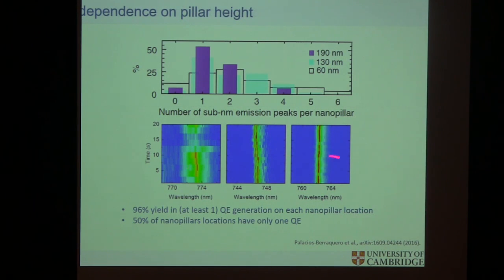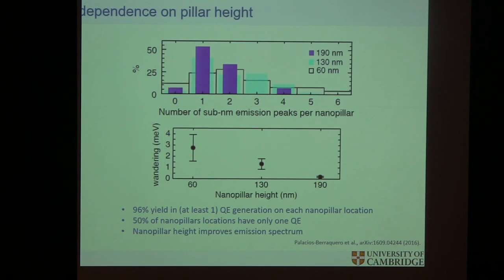The second thing, more unexpected one, is the quality of the light that comes up. Higher the pillar, cleaner the spectrum. The spectral diffusion is suppressed. This is the same scale, essentially, almost. Yeah, it should be the same scale, that's right. This is for 60 nanometer pillar, 130 and then 190 nanometer pillar, really stretched, and then you have nice clean profile. And this is the spectral wandering.